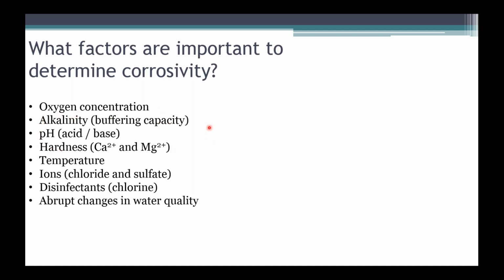Factors like alkalinity, pH, and hardness have a similar function, where at very low alkalinities, for example, you can promote corrosion, but then sometimes at very high alkalinities, you can promote corrosion as well because of increased dissolved inorganic carbon concentrations. Really, these are like oxygen in the sense that there's usually a range that drinking water facilities will try to keep these in order to minimize corrosion. Higher temperatures cause corrosion rates to be faster, and this is actually one of the principal factors that guides corrosion rates within distribution systems. And then ion concentrations, in particular chloride and sulfate, can be important to corrosion because they cause the corrosion products to be more soluble within the water. Okay, and then finally, abrupt changes in water quality can also sometimes promote corrosion.